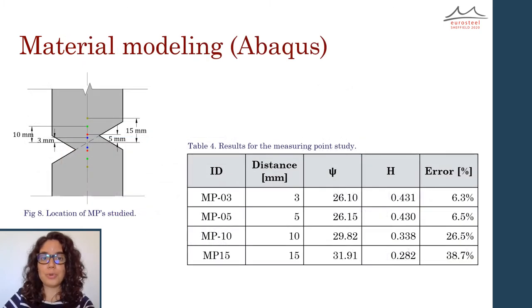Another preliminary activity completed was the sensitivity study of the location of the measuring points, also using finite element analysis. For this, it was concluded to position the measuring points 5 mm above and below the center of the neck.